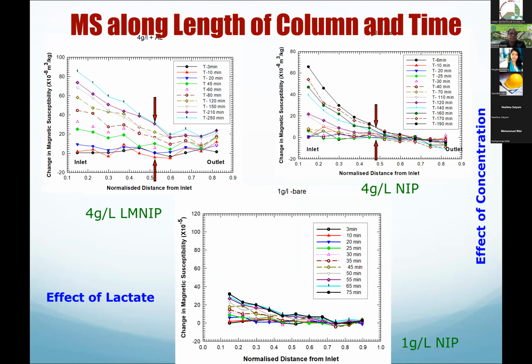But if I use 4 grams per liter lactate modified nanoiron, or 4 grams per liter for NIP, you can see this, and then 1 gram per liter NIP. You can see the concentrations here, from the inlet to the outlet. See, with different times, t equal to 3 minutes is here, and in 10 minutes this becomes, you look at 210 minutes, you see a lot of iron has transported into the sand. So here is 4 grams per liter NIP.